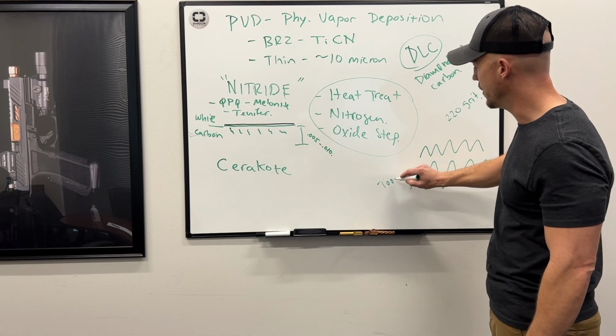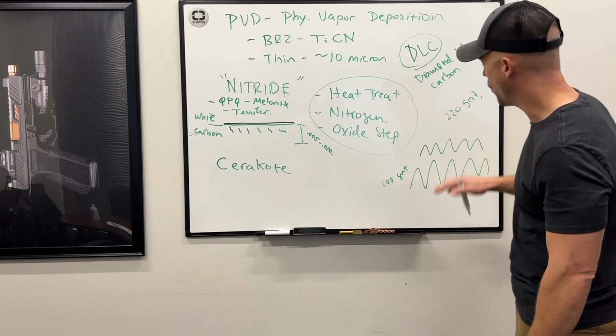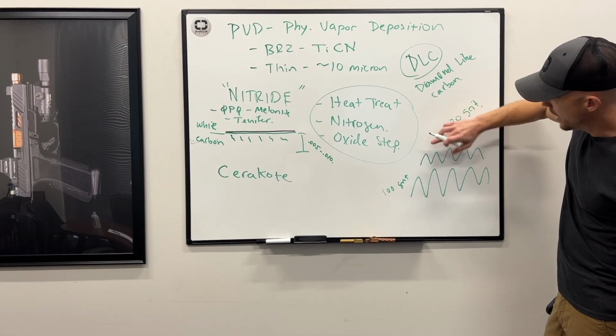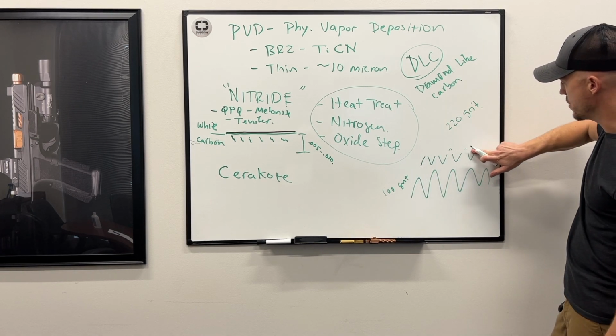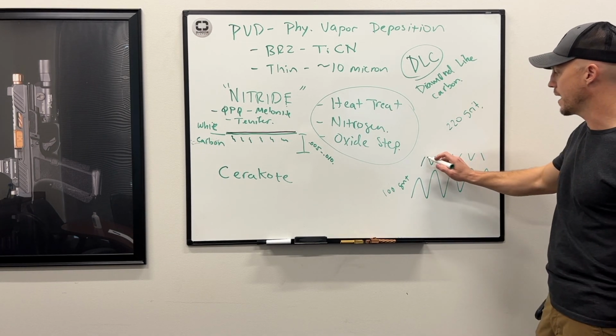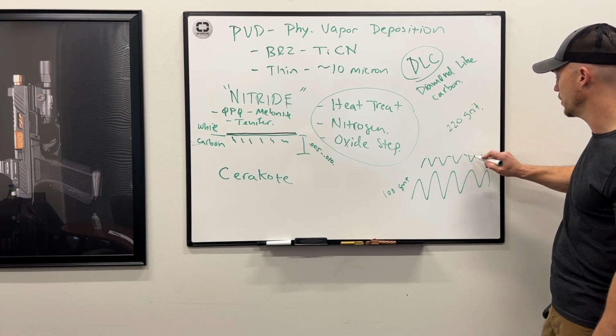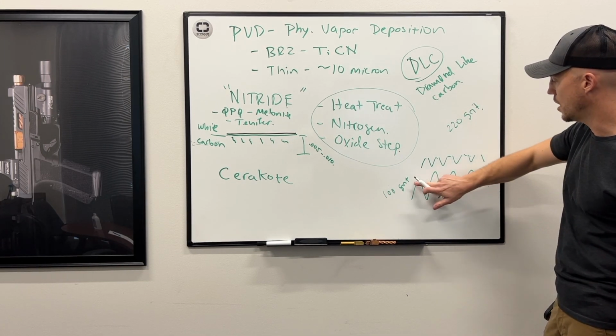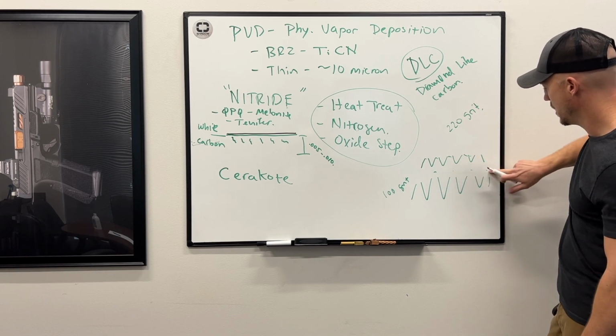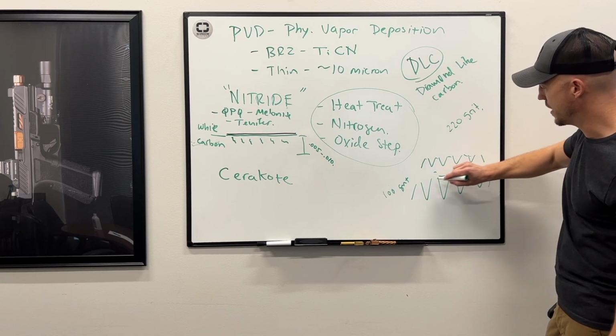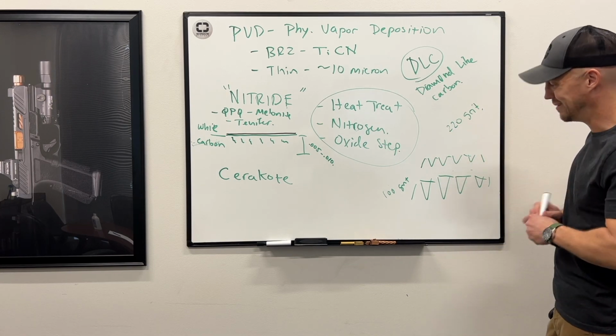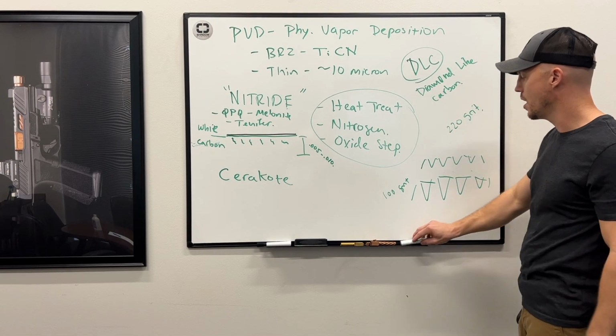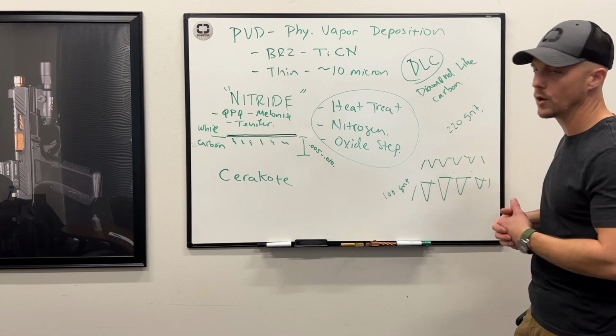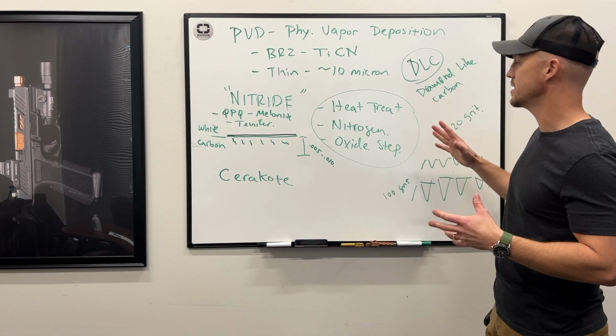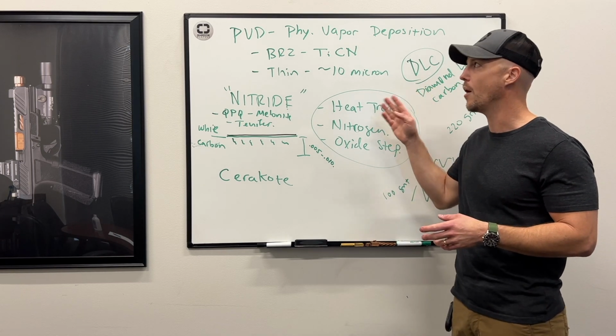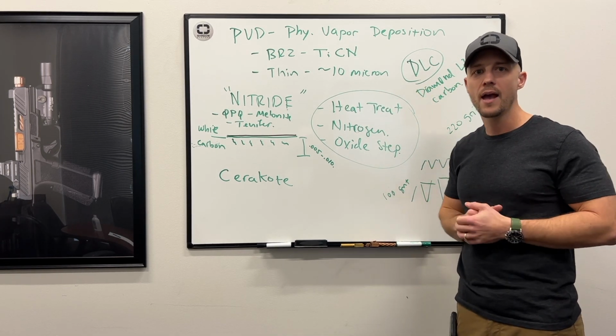And the reason this matters, when the parts are wearing and rubbing together, these peaks get knocked off, right? You can imagine that. So the amount of material I have exposed on a finer grit is a lot less than the amount of material I have exposed on a bigger grit, right? And so that means you just end up with less propensity to wear, less visible wear on a more polished surface. So we've experimented with different polishes. In fact, it's interesting, you can have two completely different colors come out on some of the PVD stuff just by changing how you prep the material.